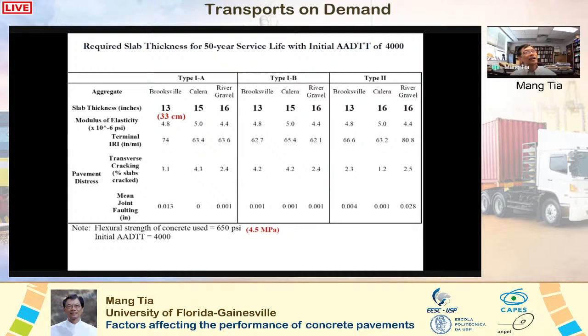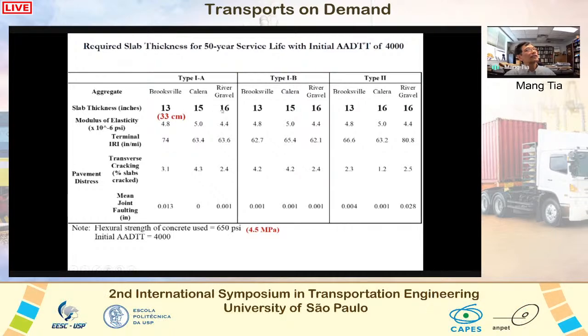If you use the right aggregate, you can have the same strength, and the concrete is going to perform much better because it has a lower coefficient of thermal expansion. So a big difference: 13 inches versus 16 inches. Now the rest of the analysis is going to be done using this good aggregate. We want to see if we can really design a concrete pavement that can last for at least 50 years, and let's do it with this good aggregate.